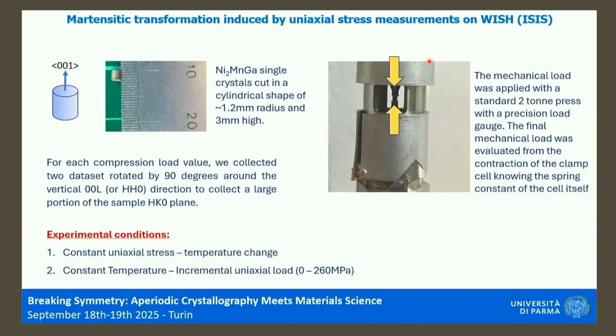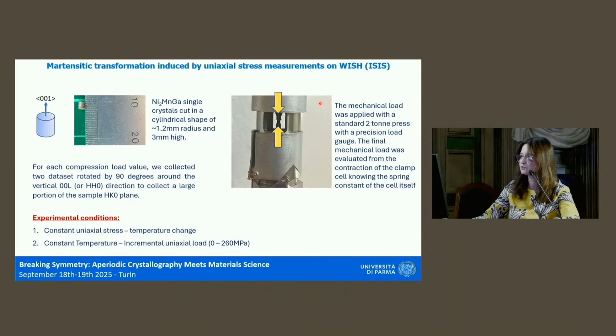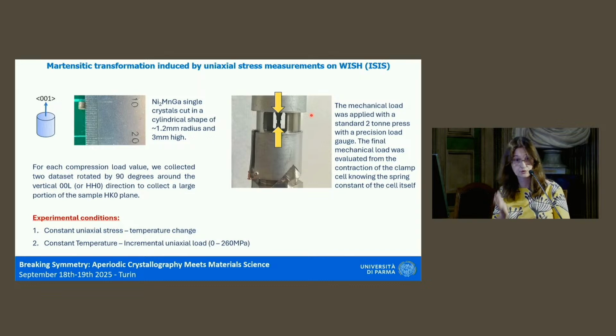In this case, we obtained from the Finland group a nice single crystal with this cylindrical shape. The growth direction was 001. You can see here this picture representing the crystal. And we fabricated a homemade clamp to accommodate the single crystal, you can see here, in order to apply a uniaxial compression in order to trigger the martensite transition. I recall that the martensite transformation temperature is around 200 Kelvin. So our proposal was to induce the transformation at room temperature by the application of a mechanical load.